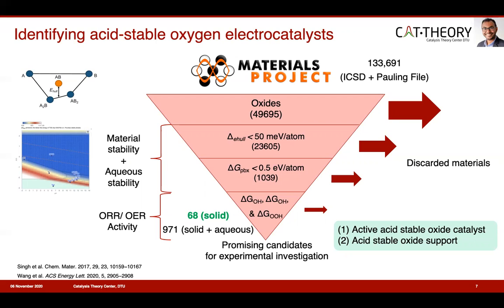Ideally, a criterion of less than 0 is preferred, but in a benchmark study of DFT-predicted aqueous stability versus experiments, it was shown that materials with predicted aqueous decomposition energies of up to 0.5 electron volt per atom could potentially be stable against corrosion in experiments. This is mainly due to the large solid-solid structural reorganization barriers originating from solid-only decomposition products. It is important to note that aqueous stability only indicates the bulk stability of a material and not the surface stability. Finally, it is somewhat depressing that by starting from close to 50,000 oxides, we only have 68 acid-stable oxides.